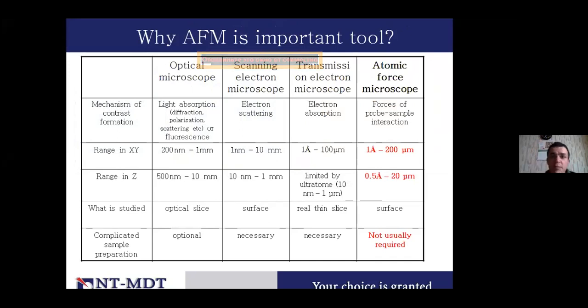And if we compare the atomic force microscope with other analytical methods like optical microscopy, electron beam microscopy, or transmission electron microscopy, the big advantage is that the resolution we can get in the XY range is down to 1 angstrom, and also below 1 angstrom in the Z direction. In atomic force microscopy, we don't go inside the sample, but we measure the surface and some properties a few nanometers below the surface. The good point is that you don't need special sample preparation. You can just cut some material, make some preliminary polishing, and measure it.